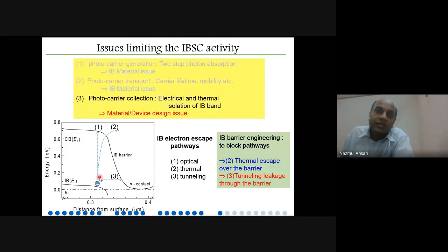Another process: if this gap is narrow, then before exciting the electron by light, process one, there is excitation by heat, so you have thermal escape of the electron. That is also another loss. So processes 2 and 3 we don't expect. This pathway is the one we expect, but most often we end up with 2 and 3 because these are fast processes.